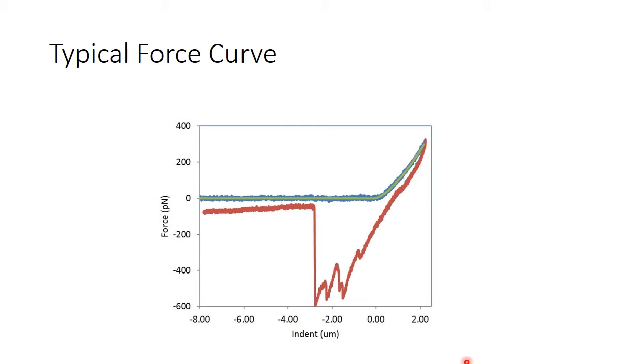This is a typical force curve. We are plotting the force applied by the tip versus the indentation of that tip into a sample. We approach the sample in this horizontal flat region of the curve, and at some point we make contact with the sample. This is where the curve starts to bend up. And we call this portion, where the tip is in contact with the sample, the contact regime.